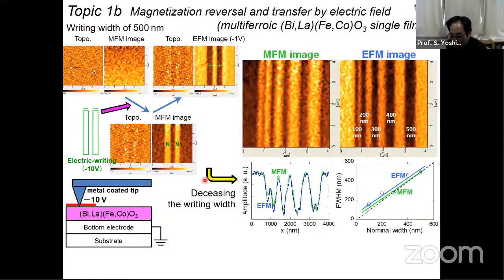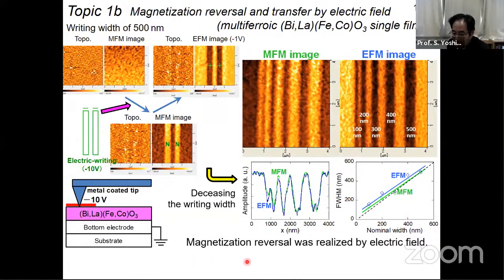And also, we decreased the width of the area where the voltage is applied from 500 nanometers to 100 nanometers. This is very important for device application because, in the case of a recording device, the bit size is very small. So it is very important to control the magnetization direction by applying the electric field to a very small area. From this data, at around 300 nanometer size, we can control the magnetization direction. So magnetization reversal was realized by electric field.